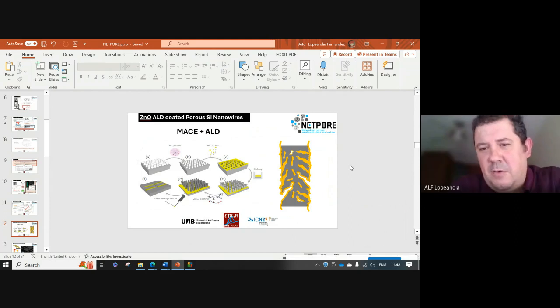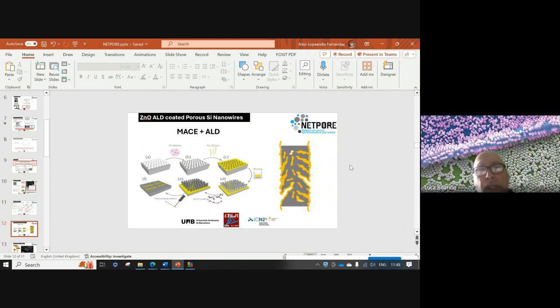So I tried to sketch it right here. This explained the behavior much better, and it resulted from the TEM analysis essentially. Compared to a silicon nanowire of 100 nanometers, we have a much lower thermal conductivity, because the material is crystalline but porous. So the confinement is in some way stopping the phonon propagation, because the mean free path at room temperature in silicon is around 40 nanometers. This is also in the literature, and most of it could be explained by boundary scattering.